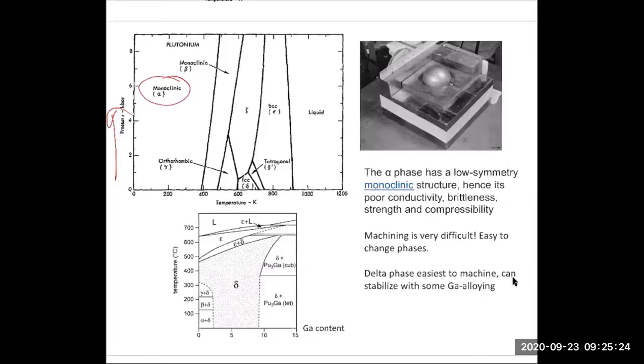So it doesn't have enough slip systems to do good plastic deformation because it's monoclinic, right? You've learned you need at least 5 slip systems to do good plastic deformation. So it's very brittle, and plutonium has to be machined highly accurately to make it into a weapon, right? Because remember that you make a sphere that then is collapsed onto itself to cause nuclear fission. So machining of plutonium is very important, and people like these higher symmetry phases in particular, like FCC, because FCC has higher symmetry, therefore you have more slip systems, and so people try to figure out how to relate these phases to each other, usually by alloying.